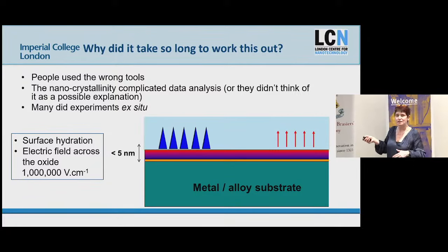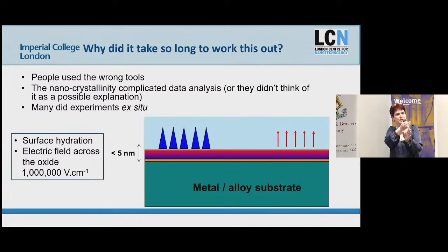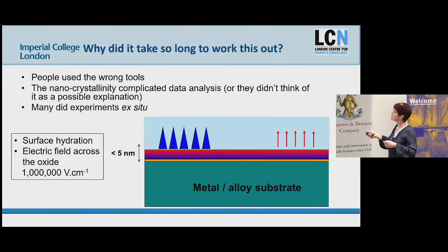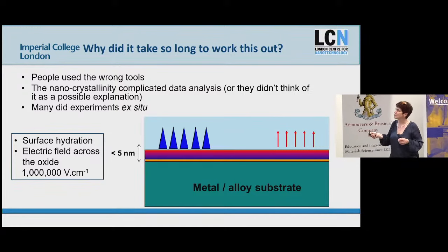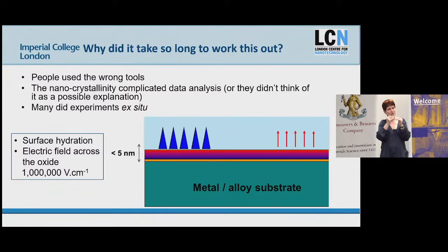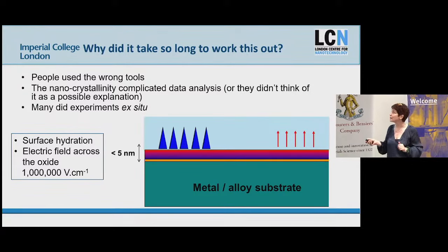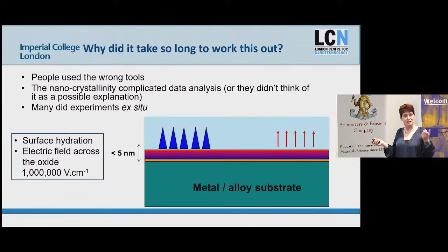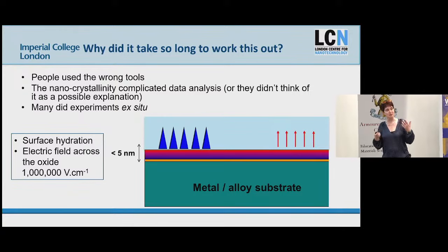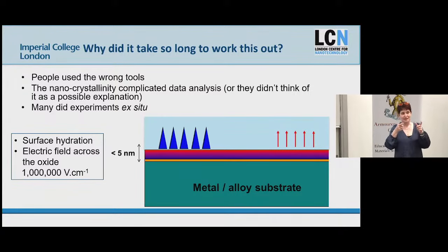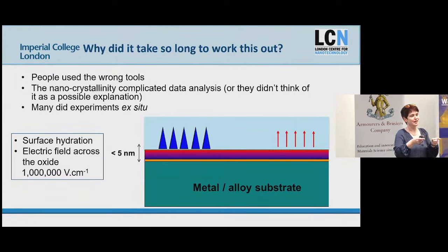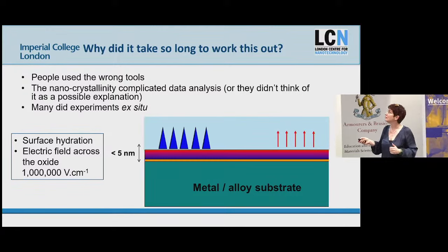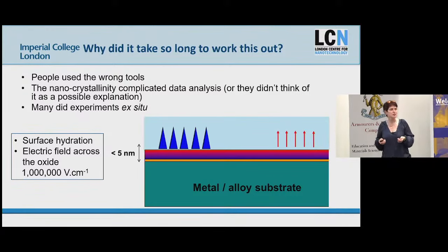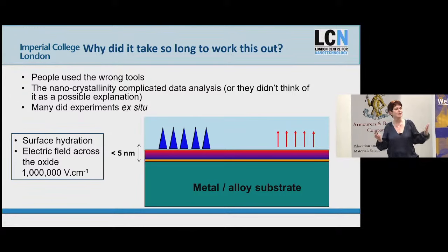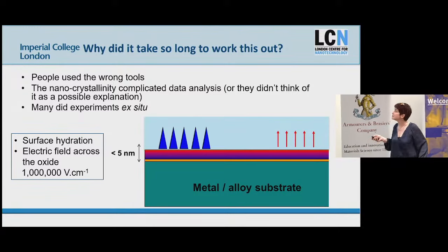But also, when you put a metal in a solution, you set up an electrochemical potential at the surface, right? And across this little oxide film here, there's about 1,000,000 volts per centimeter electric field across this tiny, tiny, tiny film. And the only reason it can sustain that is because it's this really unusual structure, right? There isn't an iron oxide that you could dig out of the ground and do this with. That would be stable, right? So the nanocrystallinity is formed because of the thermodynamics, but then it prevents the thermodynamics from taking over. So this is an interesting paradox. But this people using the wrong tools to measure things is a recurring theme, I think, in the history of controversies in science.